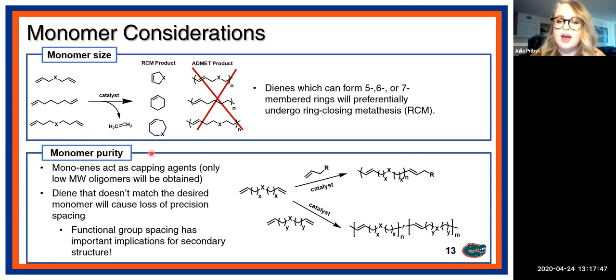The reason why: if you have a monoene contaminating your monomer, you'll form low molecular weight oligomers with the monoene on the chain end. And you can't further polymerize this chain end now. And also when the diene doesn't match the desired monomer, you'll cause a loss of precision spacing. So in this case, where your methylene spacer is 2x, if you have some 2y monomer of a different length, you'll get a random incorporation of those two different spacings, and that will cause you to lose precision spacing. And this is really important for achieving different secondary structures, which I'll talk about a little bit later on in the talk.